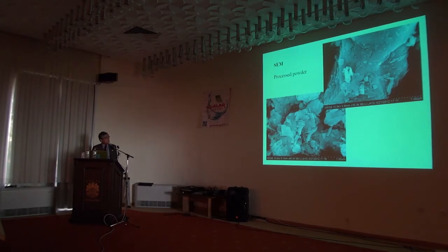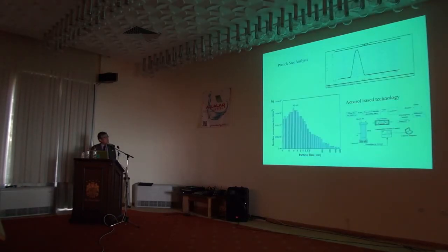And this is the scanning electron microscopic observation on the surface of the particle. You see that there are many dust-like small particles on the surface, and it's a typical observation of natural powders. And particle size analysis based on the traditional process shows that its particle size is about 1 micrometer in the center line. But if another technique, like aerosol-based technology, is applied, the particle size is about tens of nanometers. It's a very, very small size.